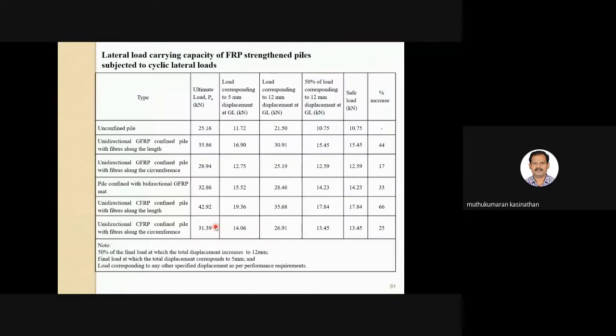And under cyclic load also, you have a great improvement in the capacity. You can look at here, a minimum 17% and maximum 66% improvement. So this was almost 80% in case of static. Under cyclic lateral load, it is close to 20% reduction compared to the static load. But still, it is much better than the conventional, unconfined pile. So we have a huge strength enhancement.